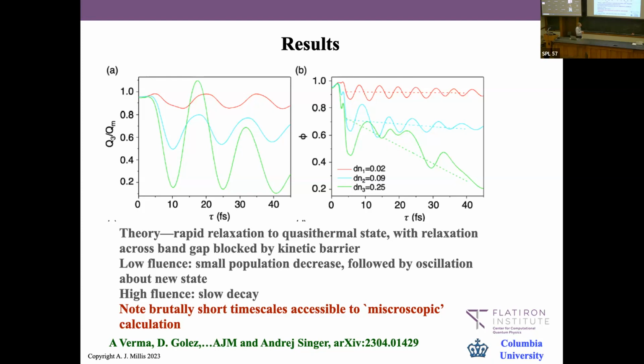With a relatively weak electric field, you make a relatively small population imbalance, and what you see is oscillations which just stay steady. With a stronger pulse, you see larger oscillations, and they decay.